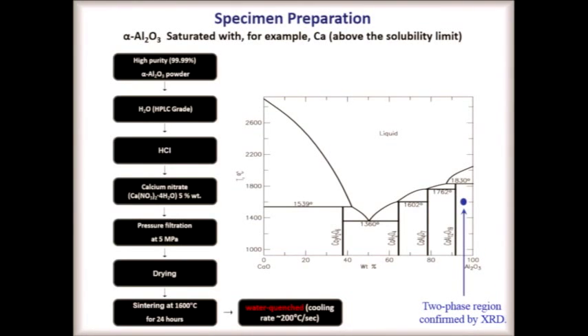The problem is, how do you measure something that is present in a low amount, but may have a significant amount at the grain boundaries? We want to know the solubility limit. That's how much is in the grains, not at the surfaces. I remind everyone that the solubility limit does not depend on grain size at all. A technique to separate them is extremely problematic. As I'll show you, the method we chose solves this by doing a lot of statistics.